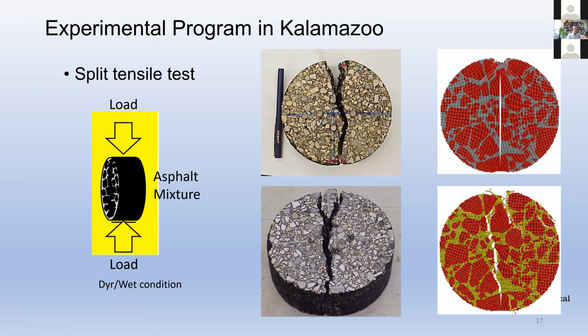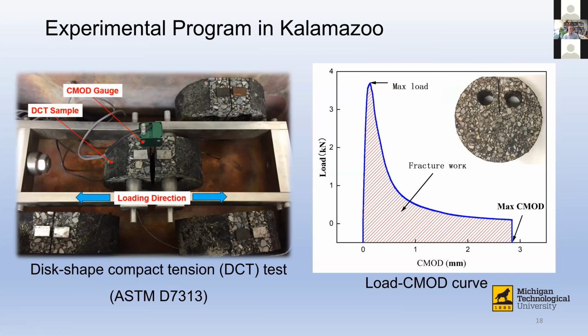And another unique one we did here is called fracture energy testing. Here you can see the test chamber we have. The sample is a cylindrical sample, 6-inch diameter like this one. We cut a notch here, and then drill 2 holes. And then of course we cut this portion off so that we can attach our strain gauge on it.